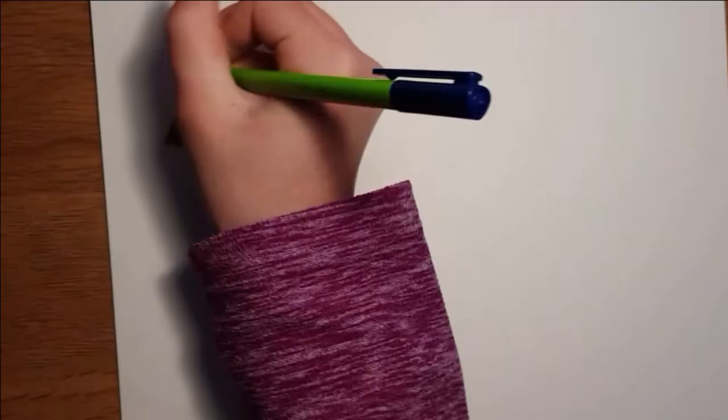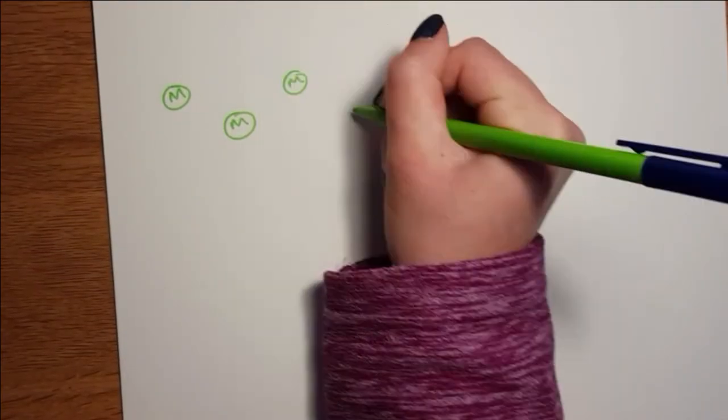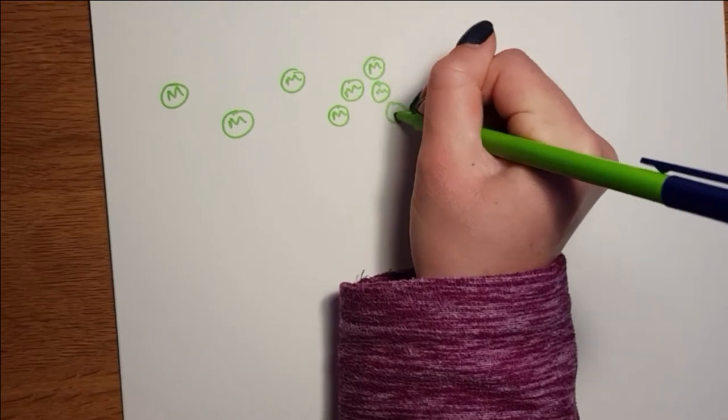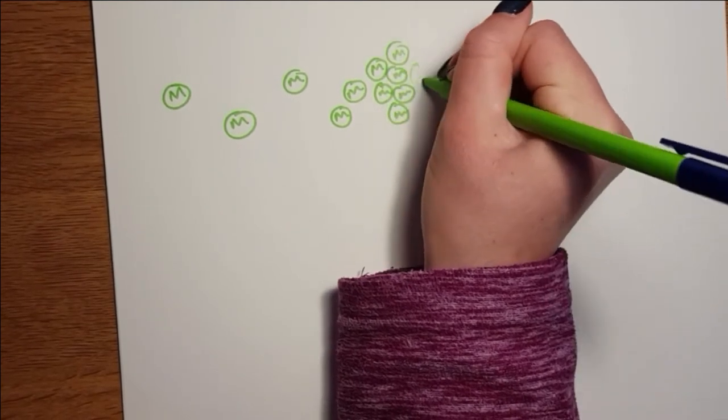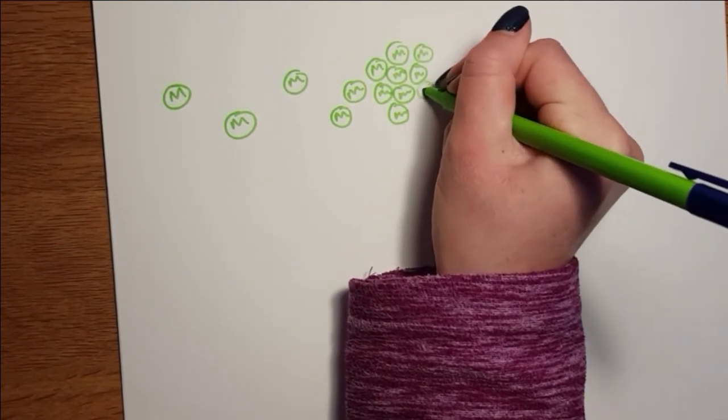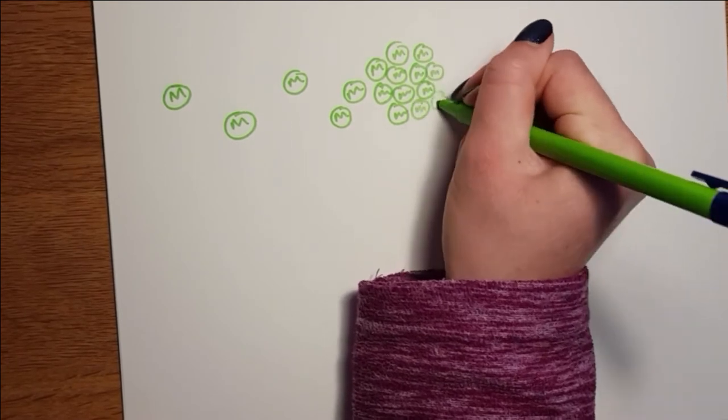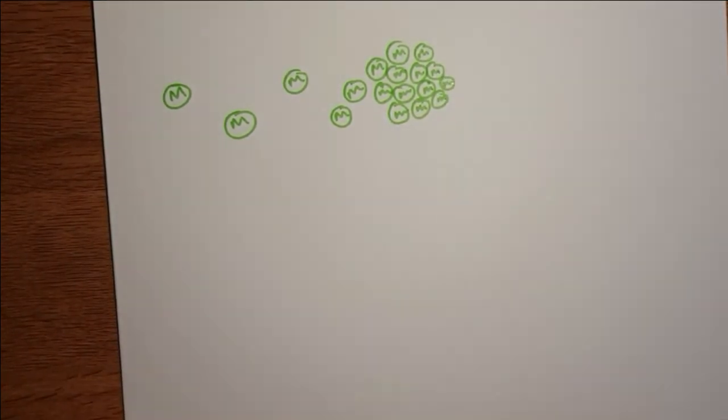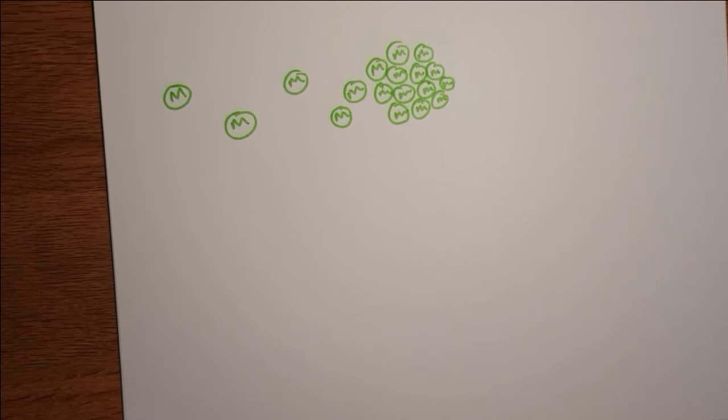The palladium metal atoms clump together to form spherical metal cores in a process known as aggregation. These tiny metal cores are much denser than most nanoparticles produced by other methods such as thermal decomposition which uses heat to decompose the metal complexes.